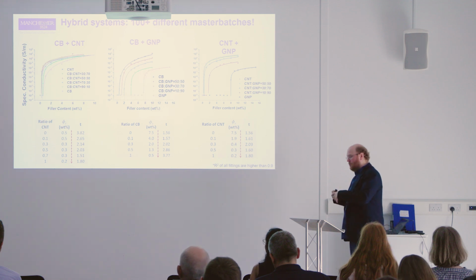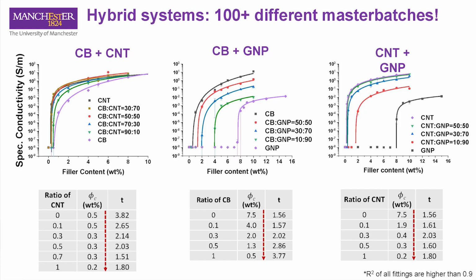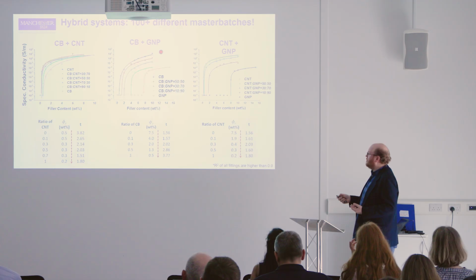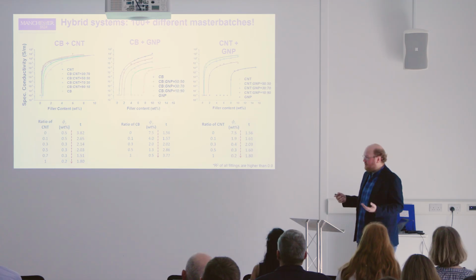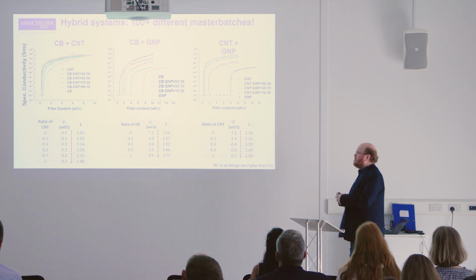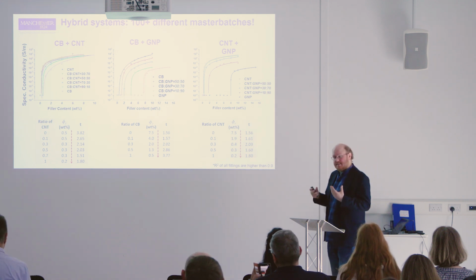So as I said, we then looked at the synergy between these. We went away, and a poor PhD student made about 100 different master batches of these materials in different ratios. So we looked at combining carbon black and nanotubes, carbon black and graphene, and nanotubes and graphene, all in different ratios. That allows us to build up this whole parameter space of: is there any unexpected benefit?